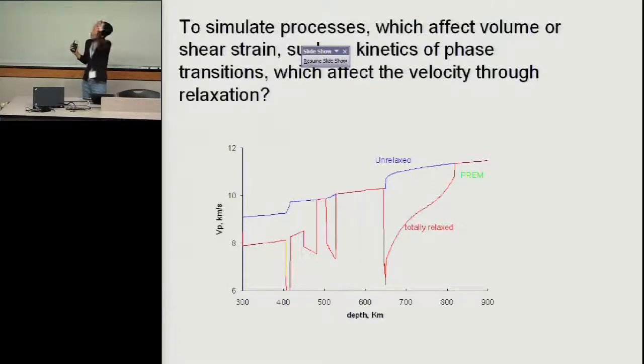And to go beyond, what can affect velocities? There's one thing that I haven't seen any simulations of, which is the inelasticity. The reason inelasticity is important is that the measurements using high frequency methods, gigahertz interferometry or Brillouin scattering, are really high frequency, but the seismic frequency is millihertz. So if there is a frequency difference, which we call the dispersion effect, the velocity can be slowed, if the velocity can be relaxed in the mantle. So how much do we know about this effect on the velocities?